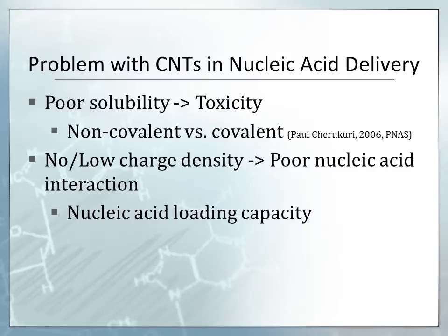So, what are the technical barriers to using CNTs for nucleic acid delivery, such as siRNA delivery? The most important thing is that they don't dissolve well in solvent, and you cannot put them into a biological system easily. Also, the insoluble nanotubes are believed to induce toxicity. It comes from the method of covalent and non-covalent functionalization, or how the nanotubes were functionalized.